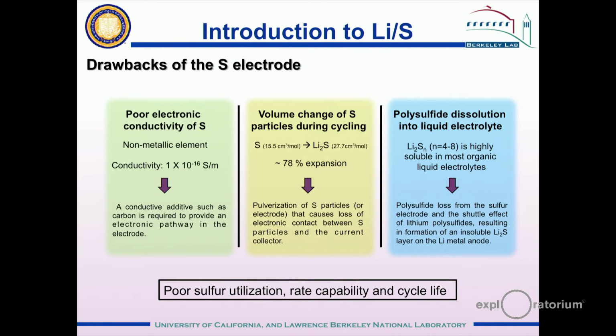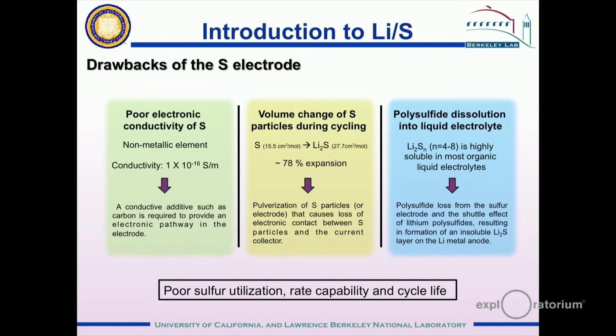electronic conductor. So we have to provide electronically conductive materials in intimate contact with the sulfur in order to have an electrode. An electrode, by definition, must be electronically conductive in order to carry out the electrochemical reactions. So we mix various forms of carbon in sophisticated ways with the sulfur in order to improve the electronic conductivity.